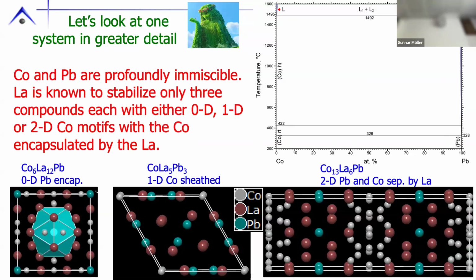So let's look at this. The only known compounds were these three. You have cobalt-6, lanthanum-12, lead. You end up with zero-dimensional lead being encapsulated by the lanthanum. You have cobalt lanthanum-5 lead-3, where you have 1D cobalt being sheathed by the lanthanum. And you have cobalt-13 lanthanum-6 lead, where you have two-dimensional lead and dense two-dimensional slabs of cobalt separated by the lanthanum. 0, 1, 2-dimensional motifs. You're dialing it in. We've been trying to have some control of dimensionality. This is at least offering it to you.